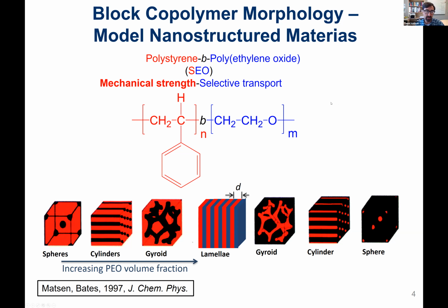If you make these materials to sufficiently high molecular weight and the polymers are sufficiently dissimilar, they will phase separate like oil and water, but because of that covalent bond, it's a single molecule, so they can only phase separate on the length scale of the molecule itself. And so that's usually, because they're polymeric, tens to hundreds of nanometers.